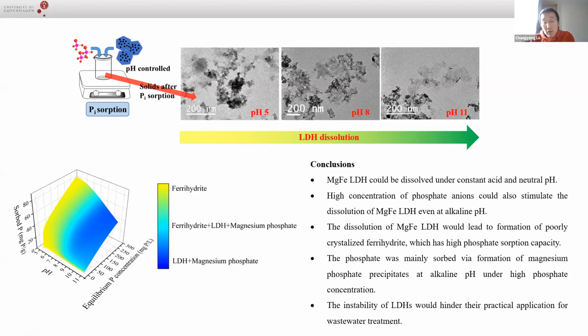And when we further increase the pH up to like 10 or 11, most of the phosphate is adsorbed on the remaining LDH. And if we go to really high phosphate concentration, phosphate is mainly removed via the formation of magnesium phosphate precipitates, and the LDH is also dissolved. So right now we have a preliminary conclusion.